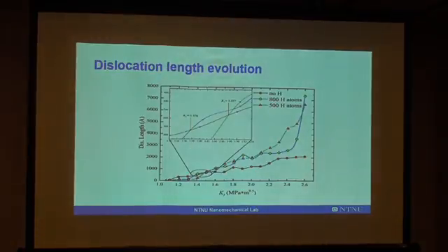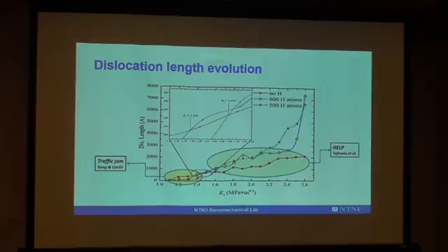And this is the evolution of dislocation length, and you can also see that the dislocation density is equivalent. And we compared the dislocation density evolution for 3 different specimens, the one without hydrogen and the other 2 with different hydrogen atoms. And initially we observed that for the specimens with hydrogen, the dislocation density will be lower than the one without hydrogen. However, if the